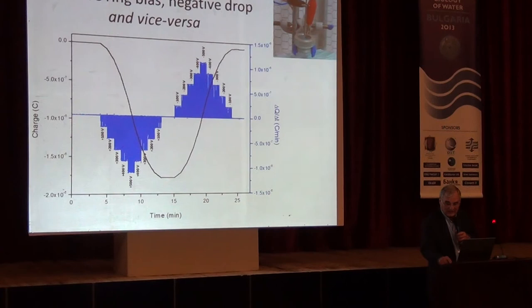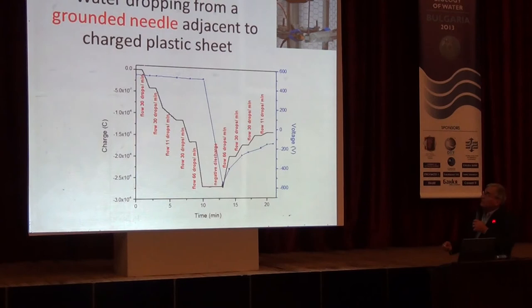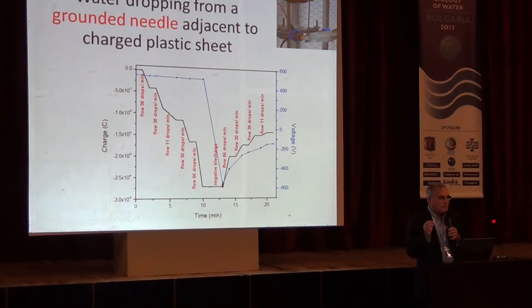Finally, water dropping from a grounded needle adjacent to a charged plastic sheet. Well, this is not so nice, even though we can accumulate negative charge, and when we apply a positive potential to the plastic, it goes back. But this is very important because it shows that whenever you have water, especially drops of water or aerosol, and you have insulators around, and any handling of plastic and many ceramics will impart charge to them, then water in its presence will be charged.